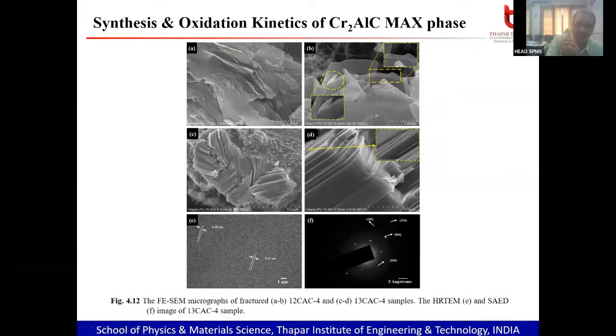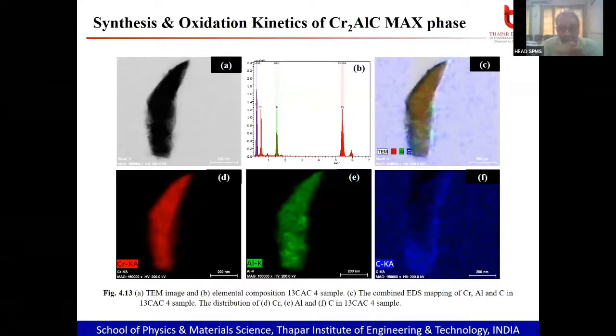This has got bended. Here also, just like the rope knots, you will find those features. So what I want to say is that in these carbides, when the intercalated layer is existing over here, you will find that a ductile part is introduced inside the material. So this is the HR-TEM, through which also we could confirm the structure. And what type of elements are present, we have also confirmed by the elemental dot mapping process also. Now you can see that this is the faceted structure, which is a typical characteristic of the carbide. But apart from this, the bending characteristics also exhibit the ductile part which has been introduced inside the material here.